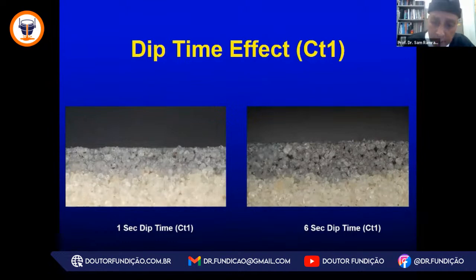Certainly the dip time. Here I'm dipping the same sand binder system for 1 second versus 6 seconds. And you can see the difference between the proud coated layer. The proud coated layer is what is nominally above the sand grain versus what has penetrated the sand grain and then the staining from the water. But we need all of this. We need the proud layer to give us the protection. We need the mechanical penetration to interlock with the grain to give us the strength for the coatings.